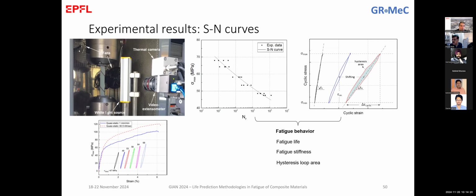Yes. So this fan of the machine is there to keep the chamber temperature stable. The other fan that we have here is to cool down the specimen, so to send to the specimen air with a lower temperature. But why do we want to do that? Why do we want to lower the temperature of a specimen? Because you need to keep the frequency as high as possible without heating the specimen. So this is the reason for also putting the specimen in the chamber.